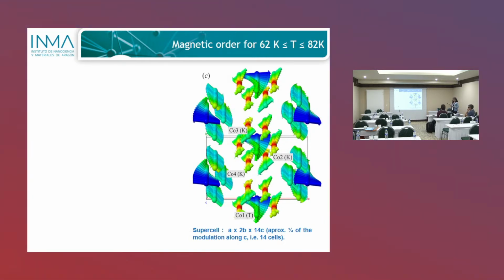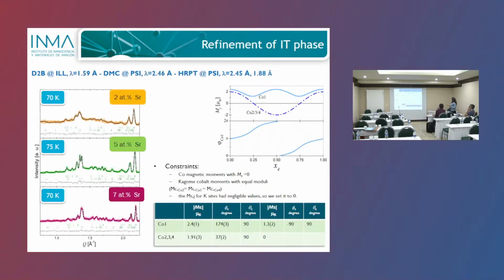This is the first time that this plateau in the magnetization is explained in terms of a magnetic model. It had been observed in other systems where the substitution site was not strontium but cobalt, for instance, by replacing cobalt with zinc, aluminum, or other cations. They also observed a plateau in the magnetization, but there wasn't a model proposed for this phase. So this is the first big result that we got from these substituted compounds.